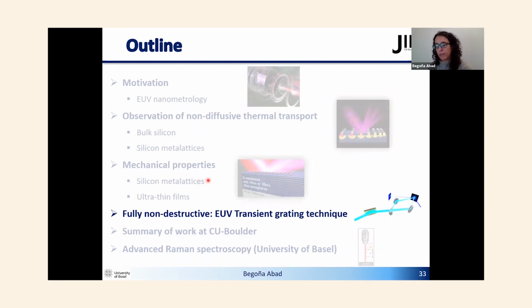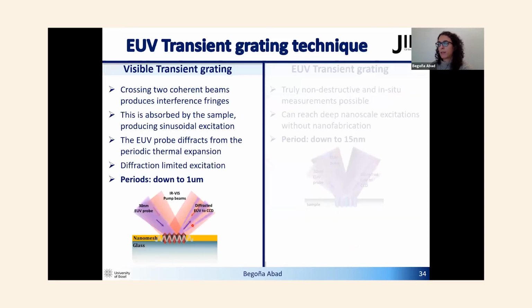Okay, and then I will briefly talk about some work I did on developing a system called the EUV transient grating technique, which is completely non-destructive. I mentioned before that we were also using a technique called visible transient grating, which is based on two beams crossing at the sample, creating an interference pattern, which creates a sinusoidal temperature pattern. From that, we can probe the dynamics with our EUV beam. But of course, this is diffraction-limited excitation, and we cannot get periods lower than 1 micron. So in order to fully explore nanoscale effects, we really need to make this period smaller.